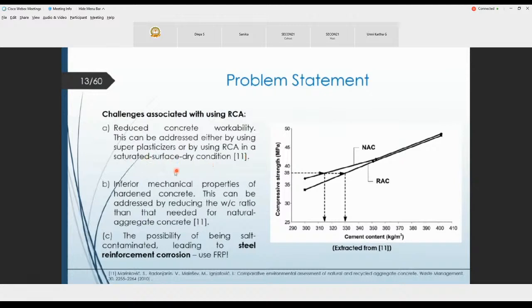saturated surface dry condition. Another challenge associated with RCA is that it has inferior mechanical properties in hardened concrete. This can be addressed by reducing the water-cement ratio compared to that needed for natural aggregate concrete.